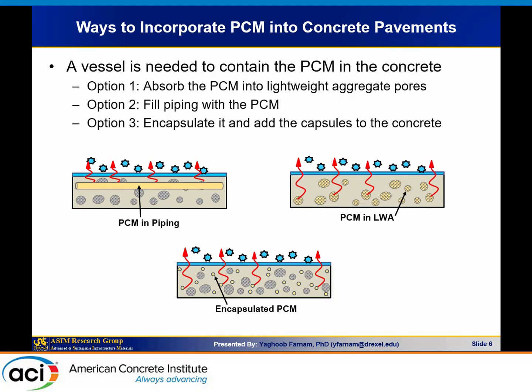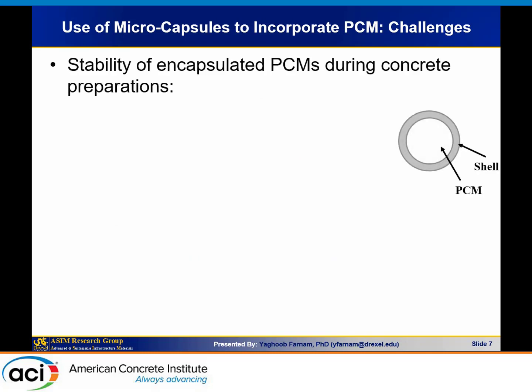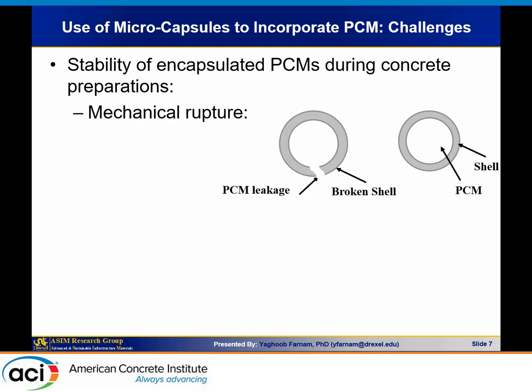But again, we have to be very careful in this case, and I'm going to mainly be focusing on encapsulated PCM, because during mixing you could break them, or there are some challenges of using them. So one of the challenges when you use encapsulated PCM: we have some PCM inside a shell, and this shell could be made of melamine-based or silica-based materials, different types of materials. One of the problems is mechanical rupture. During concrete mixing, we do have aggregate friction going on, and that might cause breakage of the shell, and the PCM could leak out, causing some problem.